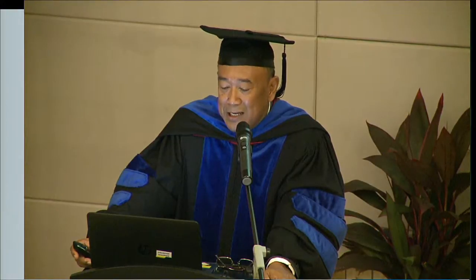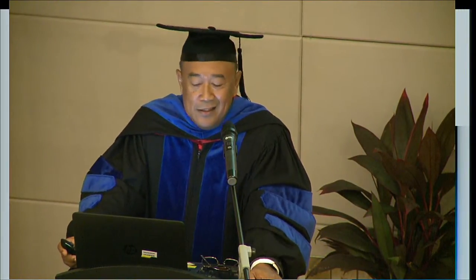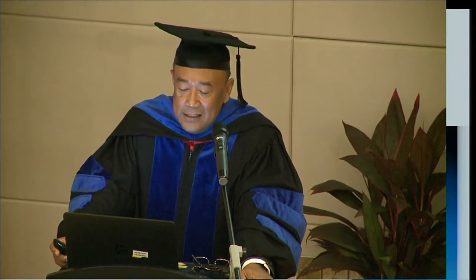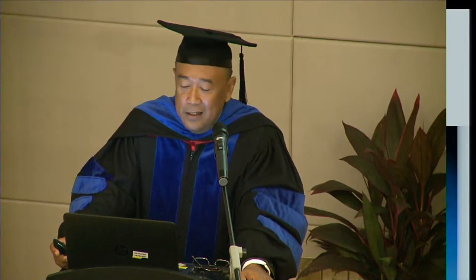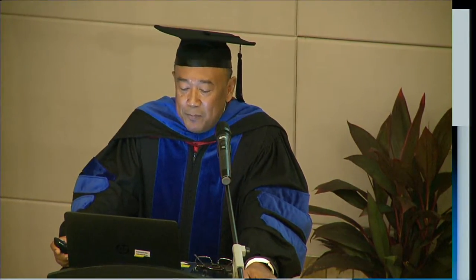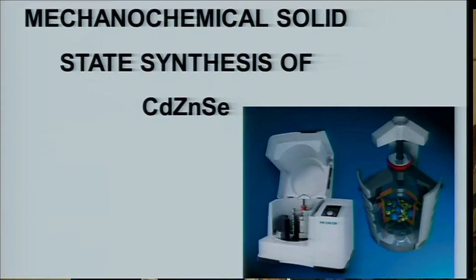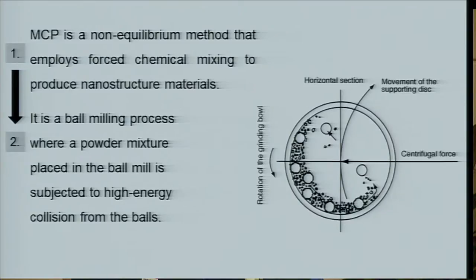And another approach that we use to synthesize material is what we call mechanochemical solid state synthesis. This is another system, cadmium zinc selenide, and we use this type of approach to synthesize in that we have eliminated any organic element in the setup. Yeah. So this is basically a solid state reaction. Yeah. And what it does is basically a ball milling process. It is a non-equilibrium method that employs forced chemical mixing, and it also produces nanostructured materials.